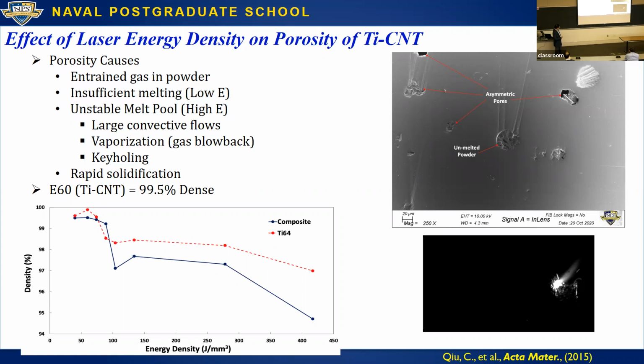And this is not our paper. This is a paper where they essentially had high-speed cameras, and they're imaging the laser interacting with the melt pool, and they can see the sparking. And the sparking is actually not sparking, it's actually splashes of metal coming out, which leads to some of these problems.